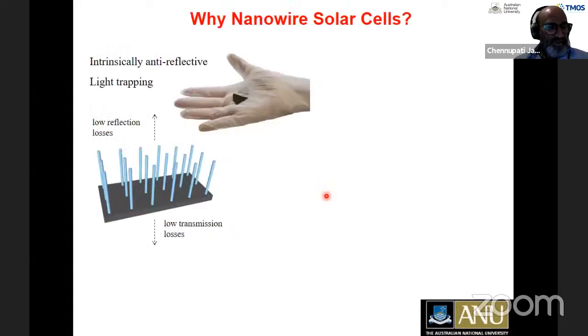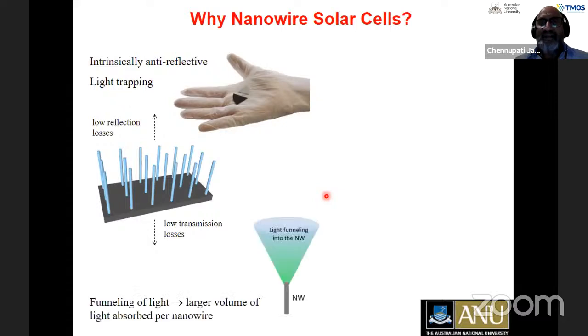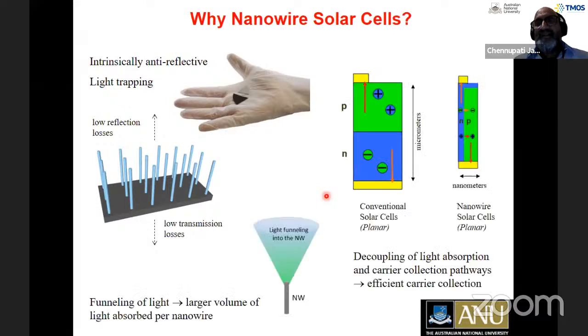Let me now move towards the nanowire solar cells. Nanowires are again opening up opportunities to make solar cells. And whenever you make solar cells, you have to make p-n junctions and you make it thick enough to absorb all the light. And that means carriers need to migrate over large distances, with contacts at the bottom and the top, and you lose some of these carriers. When you say that the solar cell is 20% efficient, 80% of the carriers are lost to defects at surfaces or impurities, for example.